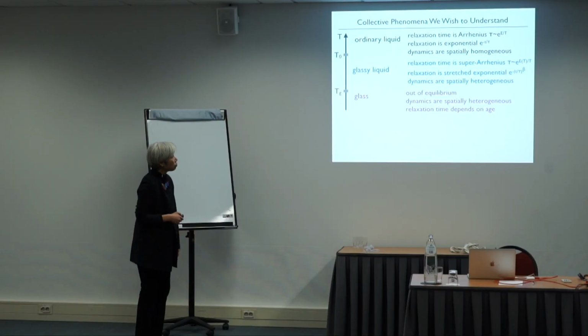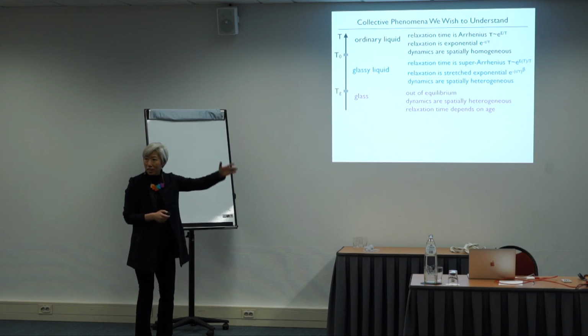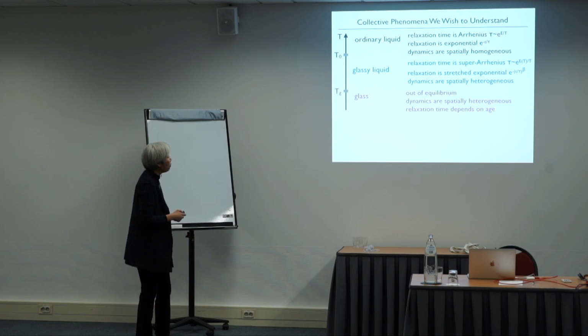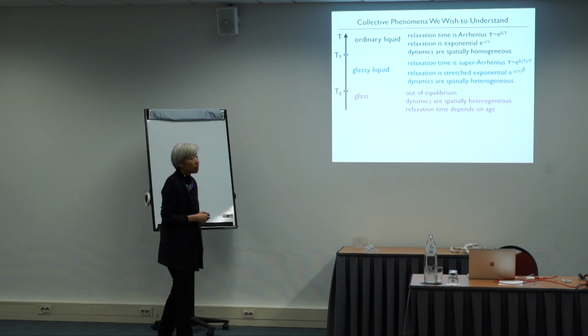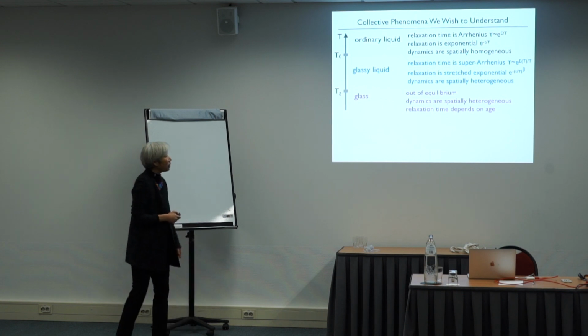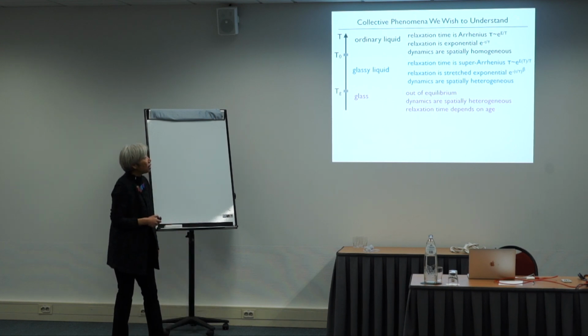Okay. Now I cool the temperature further, okay? Then I go through an onset temperature, and this is not a transition, it's just a crossover, okay? It's just a smooth change of behavior, and it changes into what I'm going to call a glassy liquid, and the way that's different is now the relaxation time is not Arrhenius. It's as if, as I lower the temperature, it's super Arrhenius. As I lower the temperature, it's as if the barrier it has to go over gets bigger and bigger. So it slows down much faster than you would have expected from the high temperature behavior.